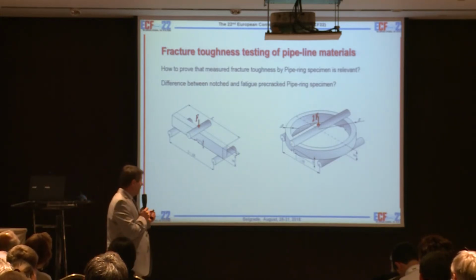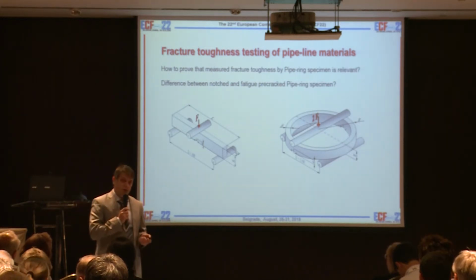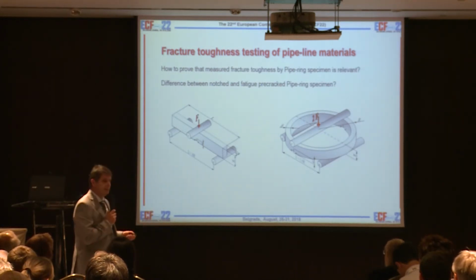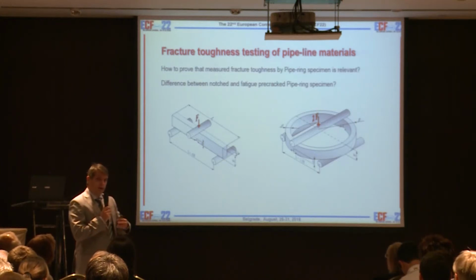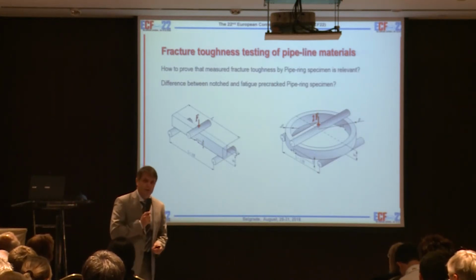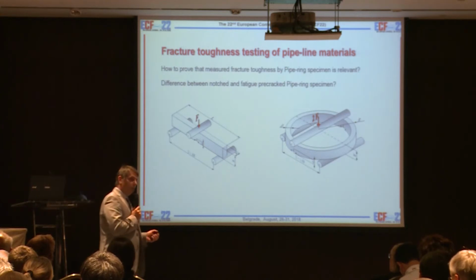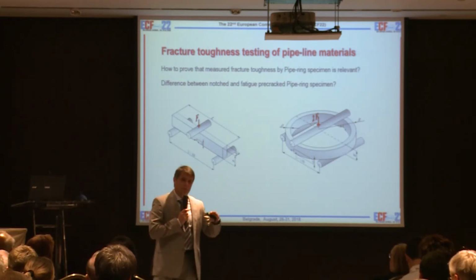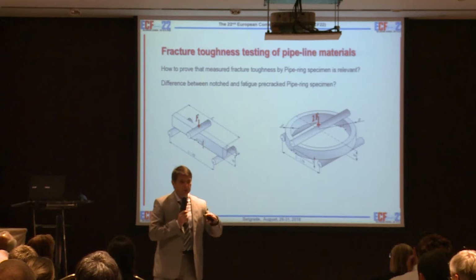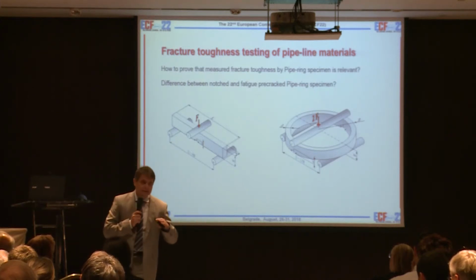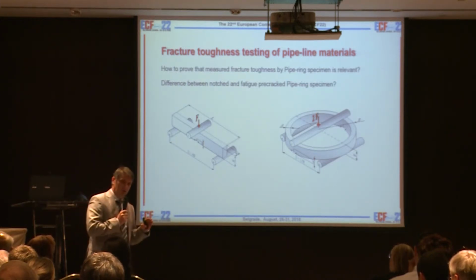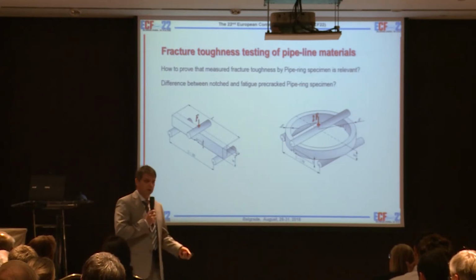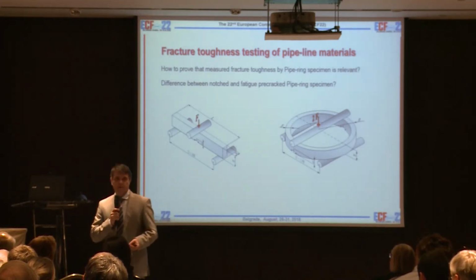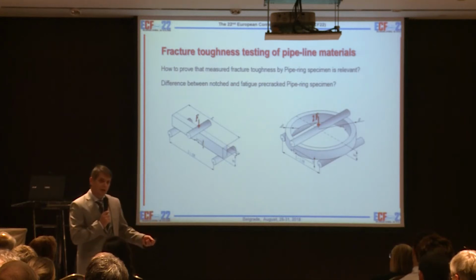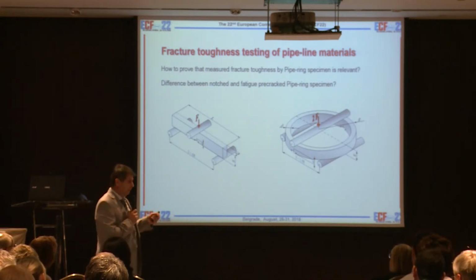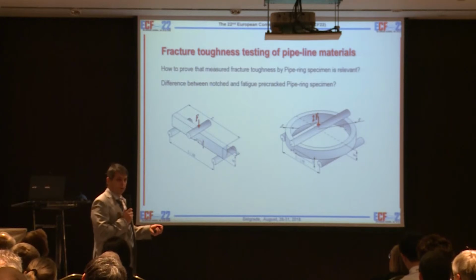But we also want to discover the difference between notched and fatigue pre-cracked pipe ring specimens. Why? Because if you are in construction somewhere in the middle of, let's say, Russia, you have no possibility to have a servo-hydraulic machine for making a pre-crack. In this case, it will be very useful to have the notch. And if you can measure the fracture toughness with a notch, you can get very fast toughness results, and this can be used in calculation. So you can check the material properties which you got from the delivery.